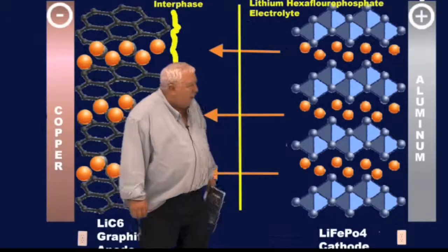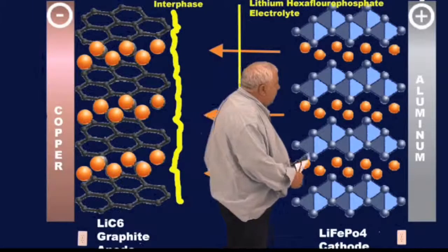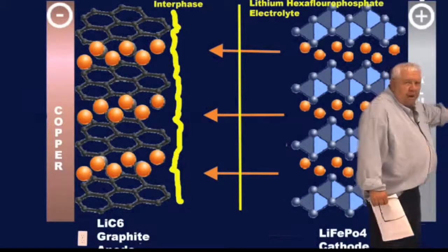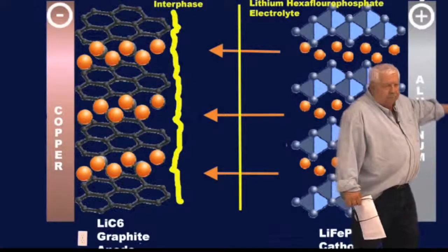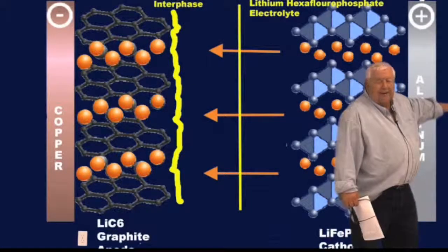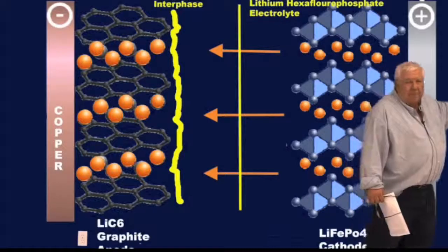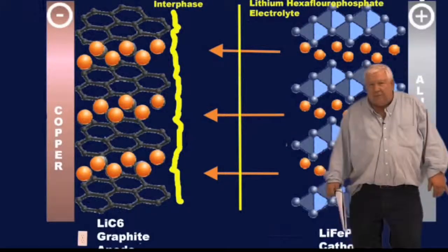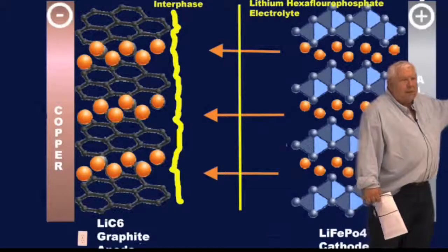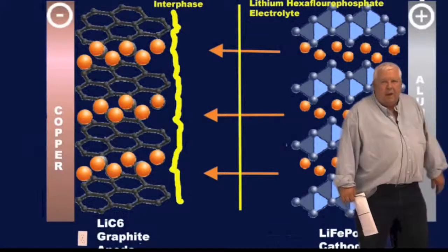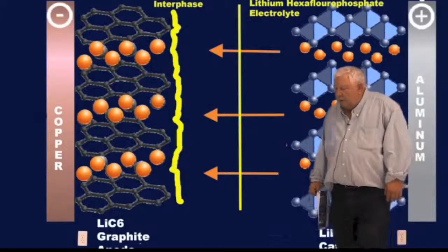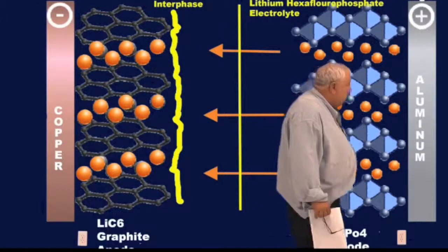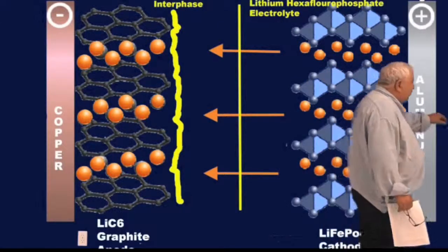At some point, it gets so hot that our cathode begins to dissociate oxygen out of this LiFePO4: 1 Fe atom, 4 oxygen atoms, and 1 phosphorus atom. The phosphorus actually stabilizes this quite a bit. It's a much safer chemistry than lithium cobalt or lithium manganese oxides, which readily give up oxygen. You've got to heat this up to twice the temperature to get it to do it.